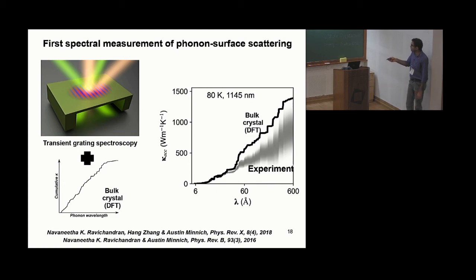So you can clearly see that this gives very rich information about how different phonons are getting scattered at the boundary. More specifically, short wavelength phonons are not getting affected a lot by the boundary, and also in the long wavelength regime, these two curves are roughly running parallel within the error bar, so even long wavelength phonons are not getting scattered at the boundary. All the reduction due to boundary scattering is happening in this mid-wavelength region. So this kind of microscopic phonon-specific information is possible with this experiment.